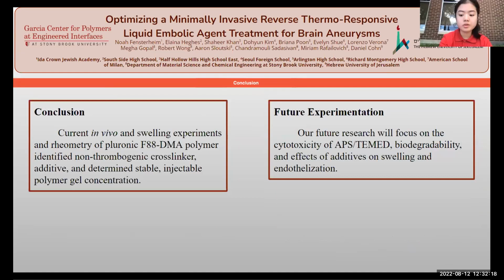So overall, we've taken 3 large strides forward in this project by identifying a cross-linker that doesn't cause clotting, determining concentrations at which our gel will successfully inject and also remain in a live organism, and identifying an additive that prevents swelling and thus mitigates the risk of aneurysmal rupture and subsequent hemorrhage. This progress enables us to look towards further refinement and new areas of exploration.